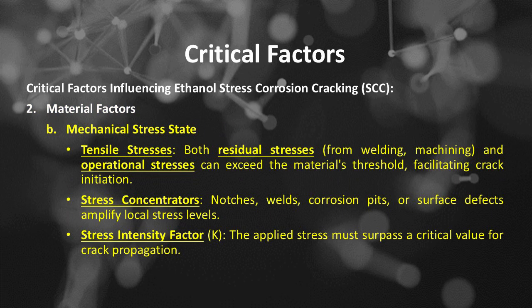Material factors. Number B is mechanical stress state. Tensile stresses: both residual stresses, from welding, machining, and operational stresses can exceed the material's threshold, facilitating crack initiation. Stress concentrators: notches, welds, corrosion pits, or surface defects amplify local stress levels. Stress intensity factor, K: the applied stress must surpass a critical value for crack propagation.